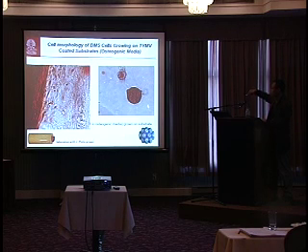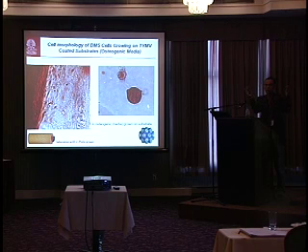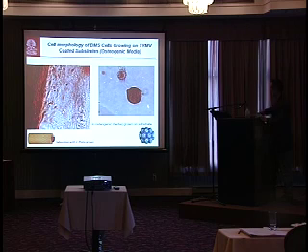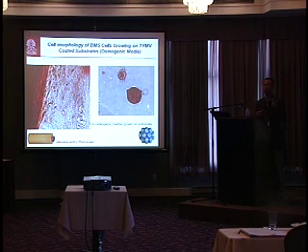If you use a rod-like particle, we form this kind of big structure. This is a centimeter long. All the cells not only form the bone, but also migrate together, giving this layer by layer structure. However, when you use the small spherical particle, 30 nanometers, they form this island-like structure. So this brings two big questions.